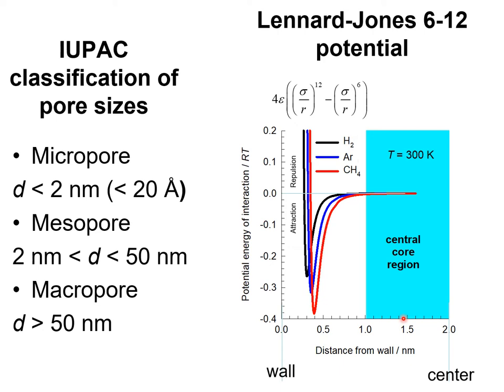We note that at the distance of one nanometer from the pore wall, the potential energies of interaction are close to zero. Therefore, for mesopores with effective pore sizes larger than two nanometers, there is a central core region in which molecule-molecule collisions are dominant and molecule-wall interactions are of negligible importance.